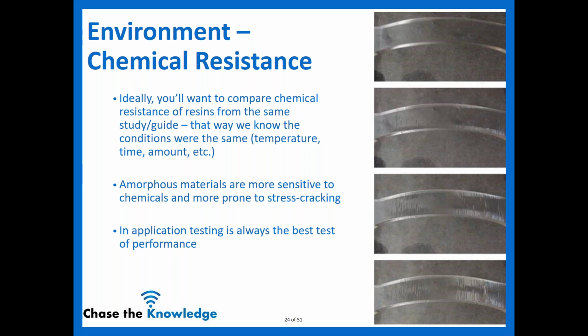We mentioned this before, amorphous materials are less chemically resistant and more prone to stress cracking. That's what the picture on the right shows, where you start to get the cracks because of the chemical exposure. And as I'm sure everyone's aware, the best way to do the testing is to test it in your application. It's the absolute best way to tell if it's going to work or not. In cases where you can't, we do refer to guides, if we have them available, to show the expected performance of that material in that chemical.